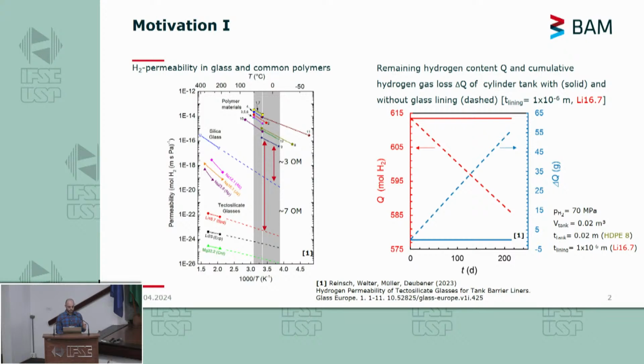Right now, you can see on the left the common polymers that are used for gaseous hydrogen storage applications. And glasses are 3 to 7 orders of magnitude better in preventing hydrogen from escaping such a storage device. On the right-hand side, you can see that already a 1 micrometer thick layer of glass could theoretically increase the storage time drastically, in the solid lines compared to the dashed ones.